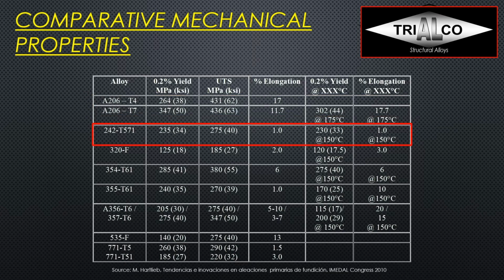Now, if high temperature strength is actually a big thing that I need and I don't care much about ductility, then I might even add a bit of nickel into it. So now we look at the 242 alloy, often used, for example, for aerospace cylinder heads or motorbike cylinder heads sometimes, things like that. I don't need elongation, but I need high strength at high temperatures. So I can see very quickly, okay, here I got 34 KSI at room temperature in terms of yield strength, and at 150 C, I still have 33. So this alloy is very temperature stable.